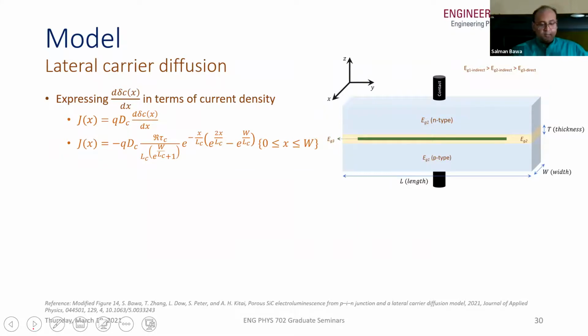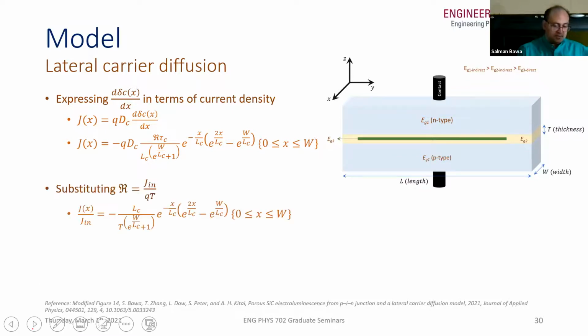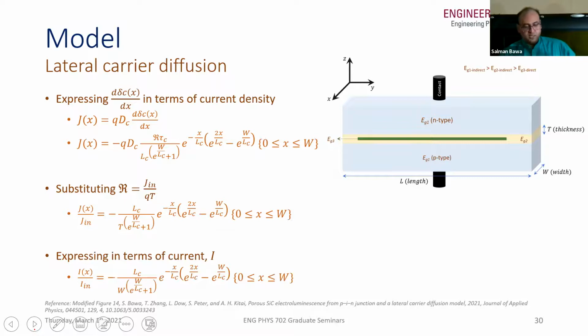Then we put the differentiation of the carrier concentration into the equation of the diffusion current density. And we substitute R equals J sub in divided by Q times T, which is the thickness of the device, to get the ratio of the diffusion current density to the input current density. And then we express it in terms of current. So this expression here is the diffusion current divided by the input current. And this is the final equation that we get, that you see on the screen.